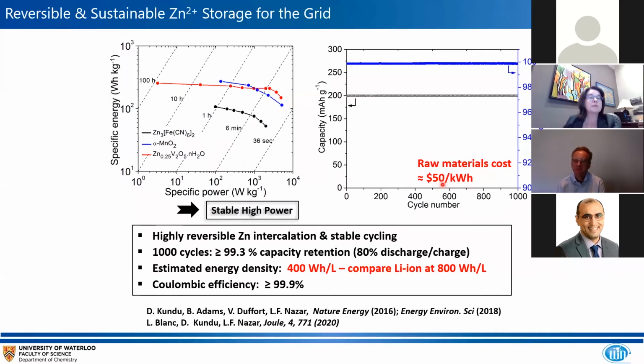And the raw materials cost is really fairly low. So the estimated energy density that we've calculated, on the basis of a lot of spreadsheets, is around 400 watt-hours per liter. And that's only half of what lithium ion is, at 800 watt-hours per liter. But the point is that these materials can be stacked much more readily than a typical cylindrical lithium ion cell.